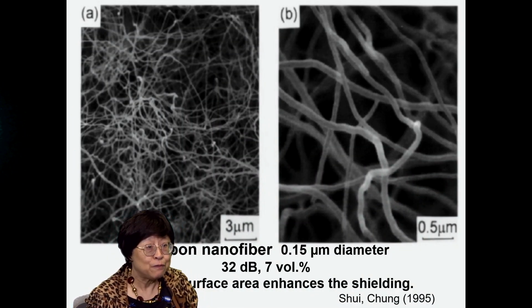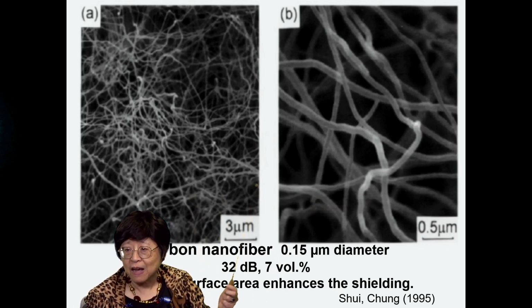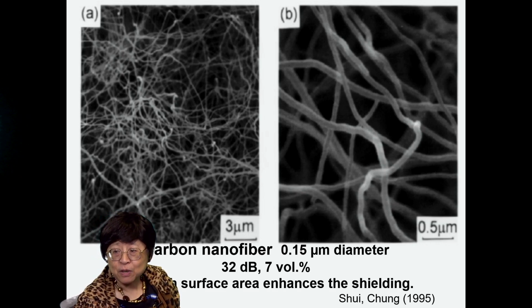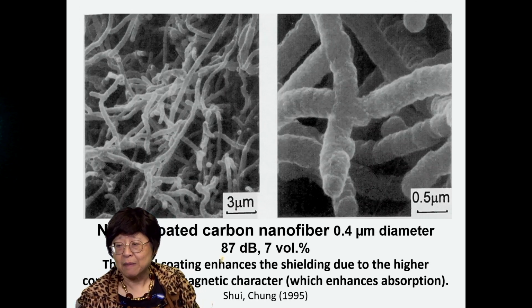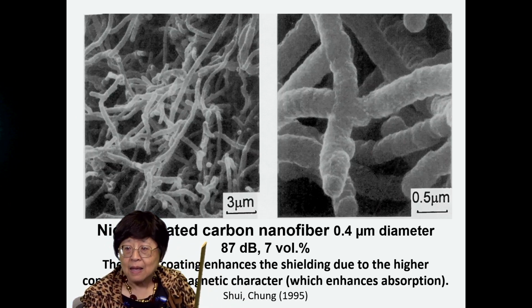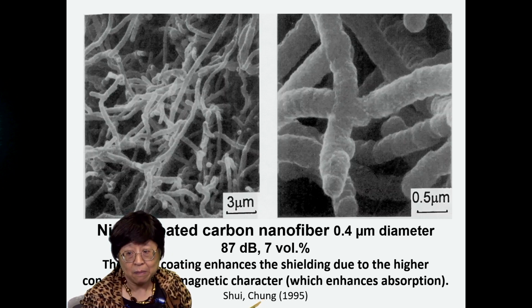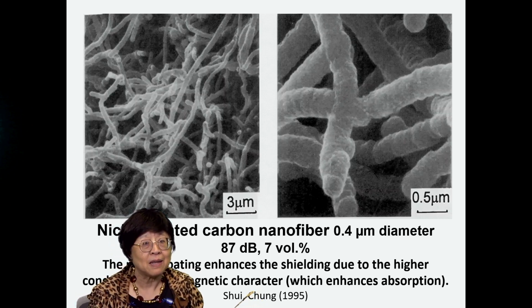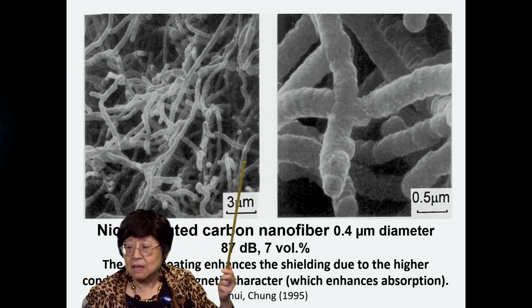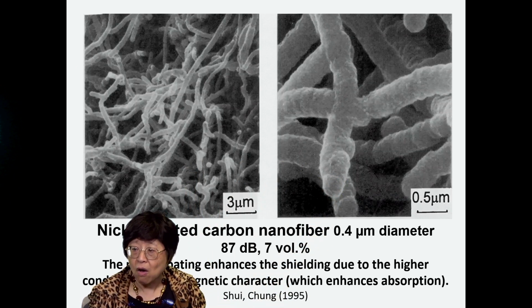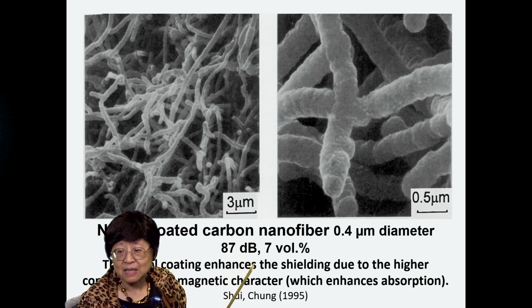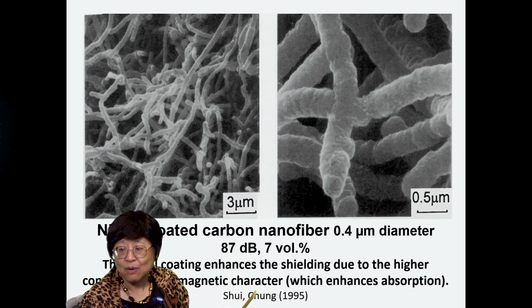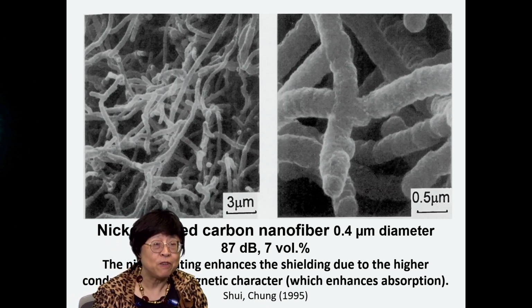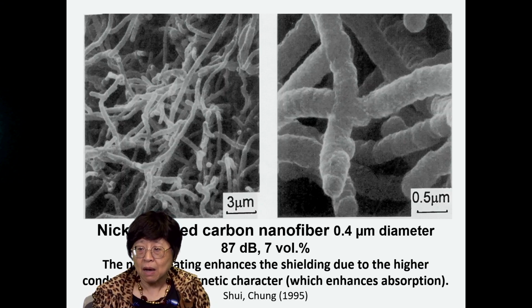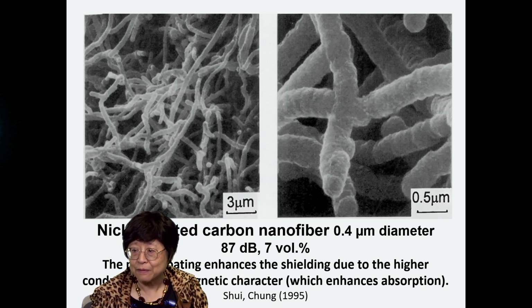And we want to push this even further. This is that same carbon nanofiber that I showed you, lower magnification and higher magnification. And to push this further, we coated this carbon nanofiber with a thin layer of nickel. Nickel is a metal, so it's even more conductive than carbon. Also, it's magnetic, and both conductivity and magnetic character help the shielding. And this is the nickel-coated carbon nanofiber, and it provides 87 dB. And even now, it is the record. It's among the very best filler materials for making composites for shielding, and that was back in 1995.